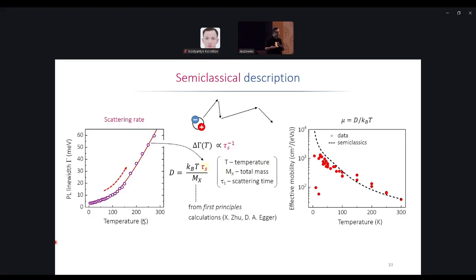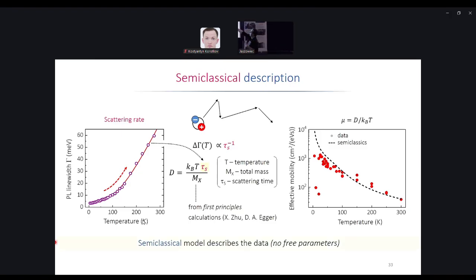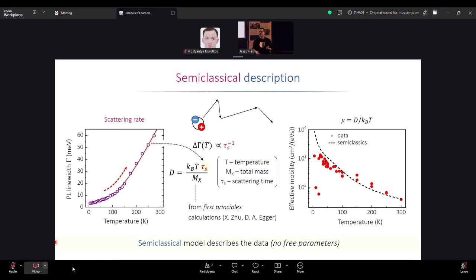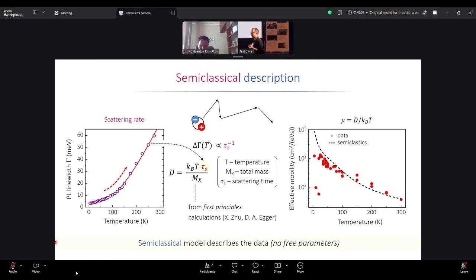In principle, you can get reasonable agreement, which, by the way, does not necessarily mean that this description is correct. It just means that if these parameters are independently inserted like this, then the semi-classical drift diffusion model could explain the experimental data. But there's one thing that we need to consider, and this we will do after the break, is the applicability of the semi-classical description to begin with.